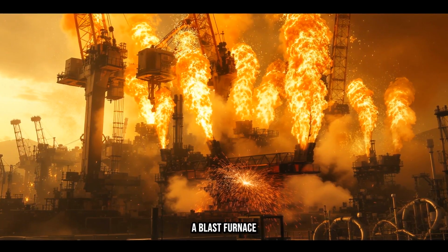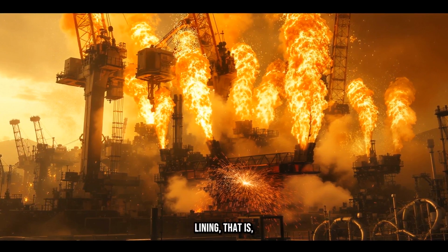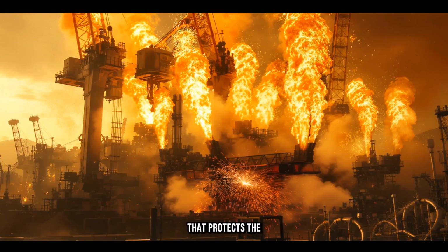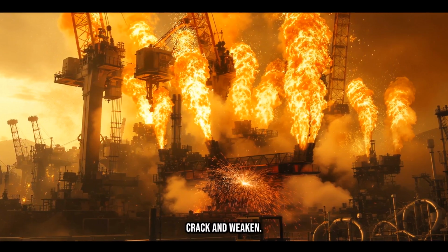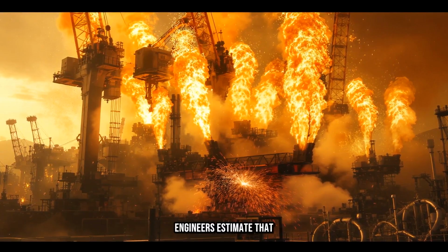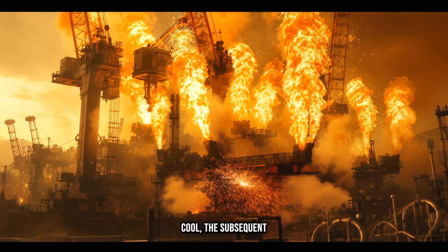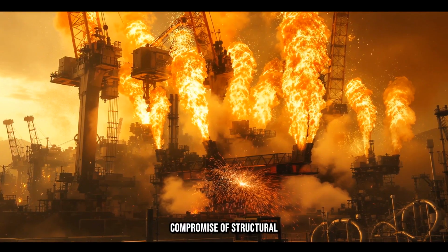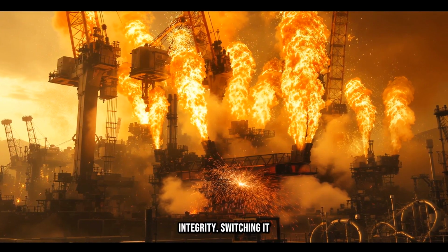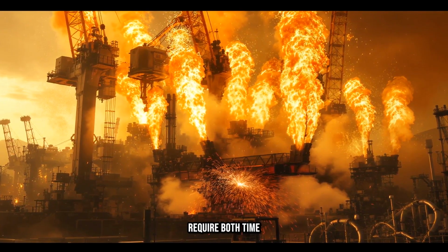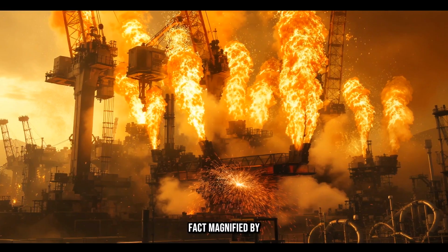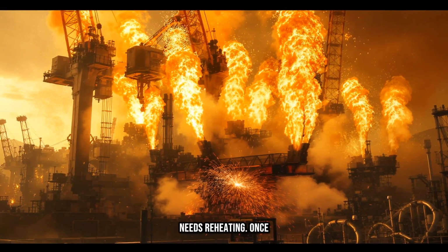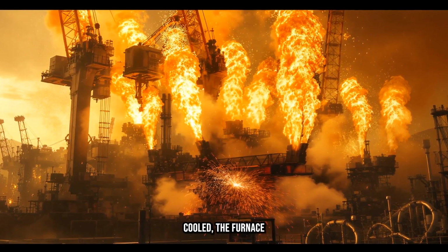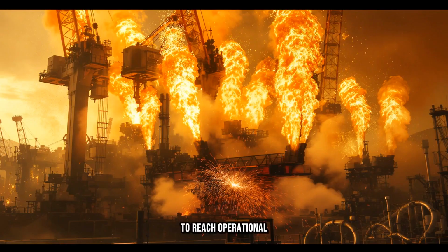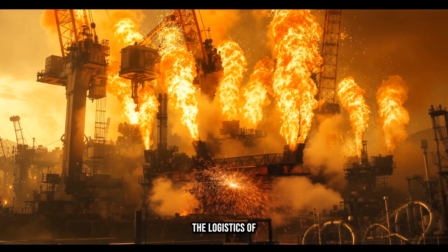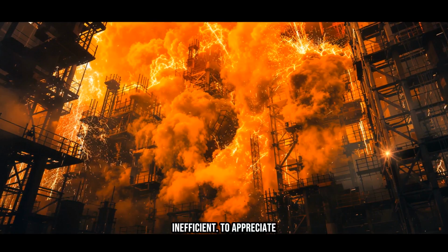When the materials within a blast furnace cool, the refractory lining, that is, the firebrick that protects the furnace walls, can crack and weaken. Engineers estimate that if a furnace were turned off and allowed to cool, the subsequent reheating could lead to a dangerous compromise of structural integrity. Switching it back on would require both time and energy, a fact magnified by the sheer volume of material that needs reheating. Once cooled, the furnace would take days, if not weeks, to reach operational temperatures again, making the logistics of a restart exceedingly inefficient.